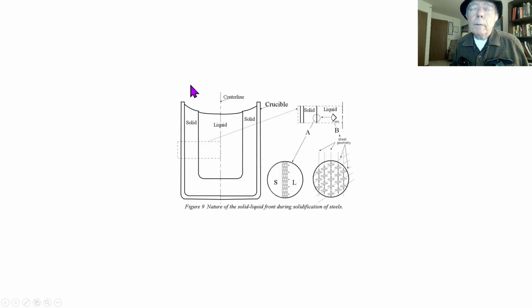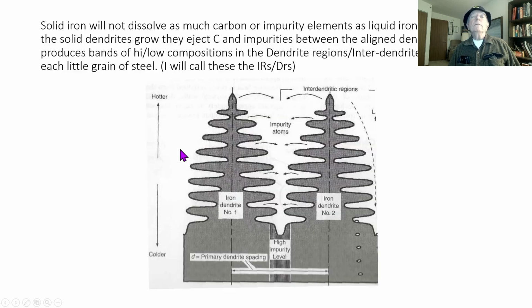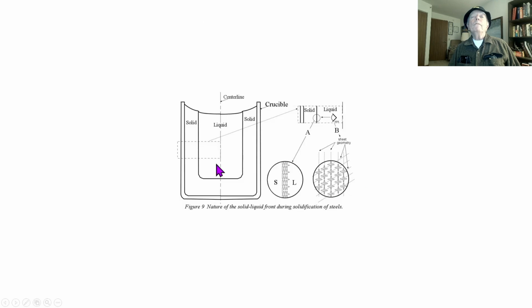Now I'm going to explain a little bit about what's going on in those crucibles that the Indians used to melt and solidify their ingots. Think about how the heat flows out of a crucible as it cools. It's going this way and this way. So the solid, after the liquid, which is initially probably up here, starts to form, the solid just shrinks in size. It grows like this from the edge with the liquid trapped in the middle.